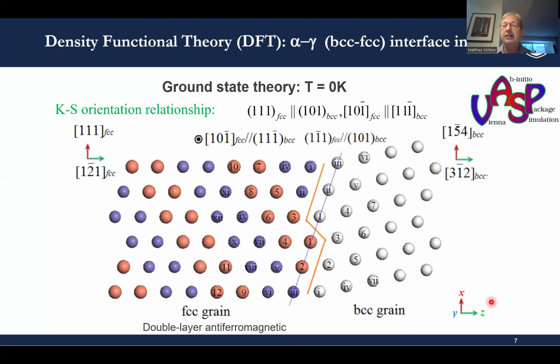If we look at iron, there are a few challenges because we have to account for the magnetic state of iron. That's not really a big deal in BCC iron, which is ferromagnetic. We can do spin polarized calculations, which are very well established. It's a little bit more challenging for the FCC phase, which should be paramagnetic, and we have to find an approximation for the paramagnetic state. An example is shown here with the double layer antiferromagnetic structure, where blue and red positions are spin up and spin down, respectively. Another approach is what are called special quasi-random structures that can be used. So there are a few different options that one has.